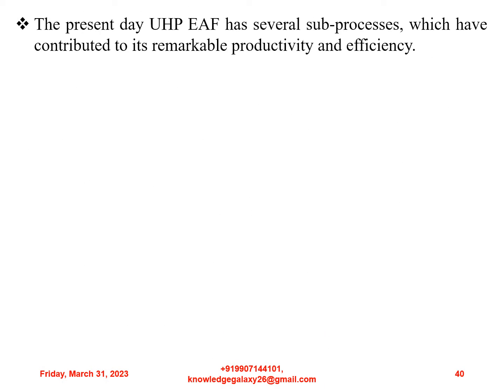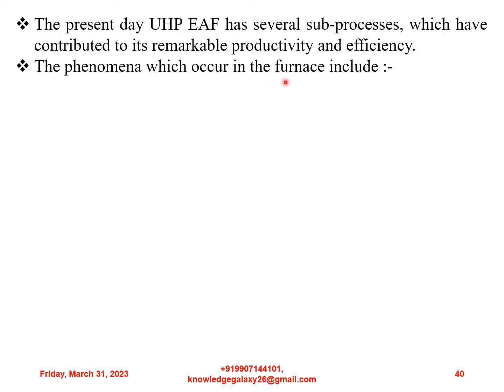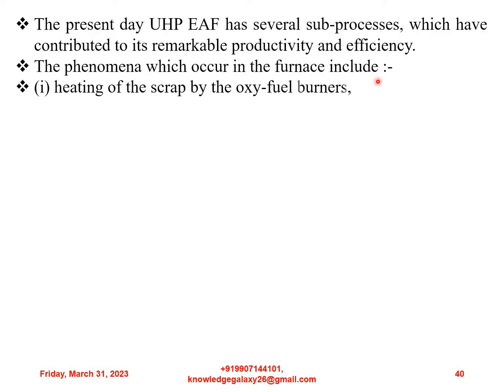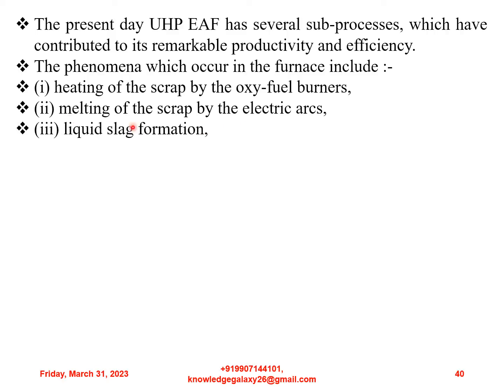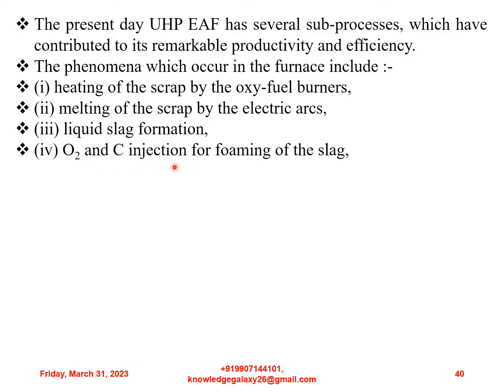The present day ultra high power electric arc furnace has several sub-processes which have contributed to its remarkable productivity and efficiency. The phenomena which occur in the furnace include: first, heating of the scrap by the oxy-fuel burners; second, melting of the scrap by the electric arcs; third, liquid slag formation. Next comes oxygen and carbon injection for foaming of the slag.